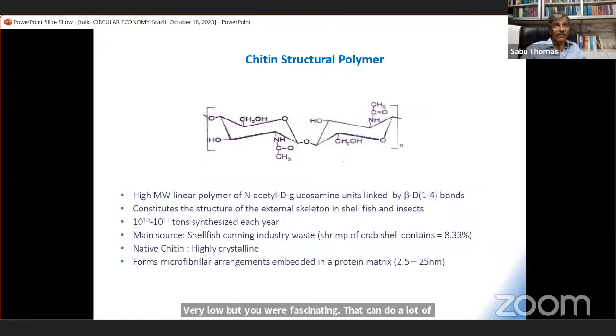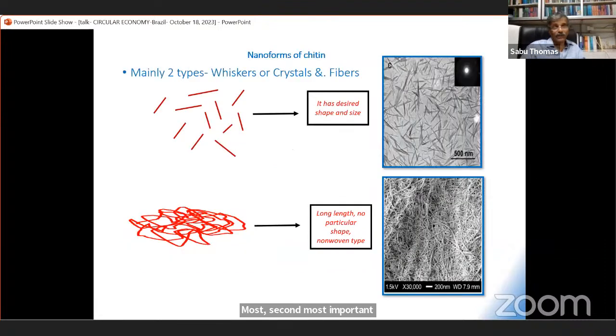And this is the second most important biopolymer in the crust of the earth. What I want to tell you is, from crab shell or prawn shell, if you do some simple processing, you can make either nanocrystals of chitin or nanochitin fibers. If you use a less harsh extraction process, particularly a light acid, you get nanofibers. If you use strong acid, you get nanocrystals of chitin. So our group is very active in extracting both nanofibers and nanocrystals.